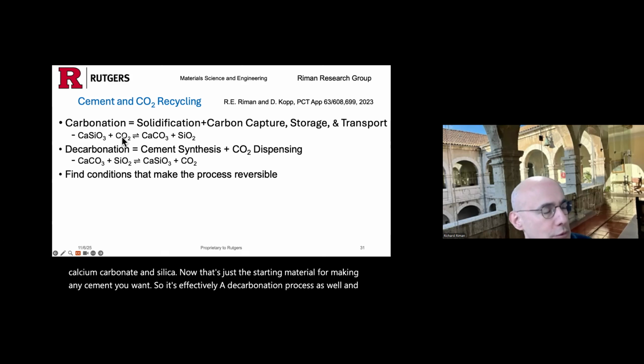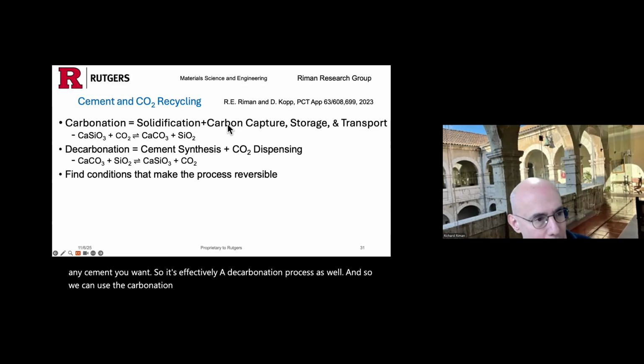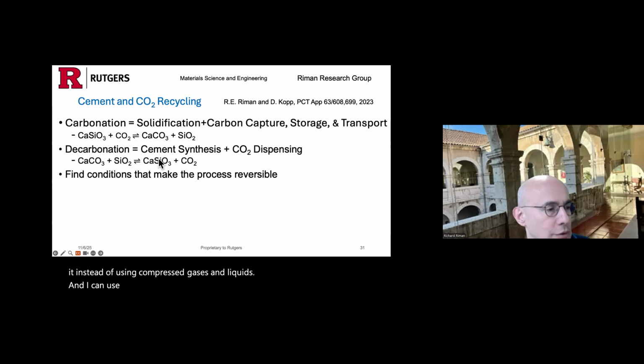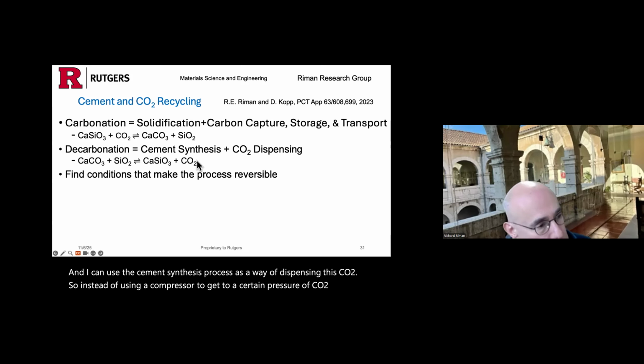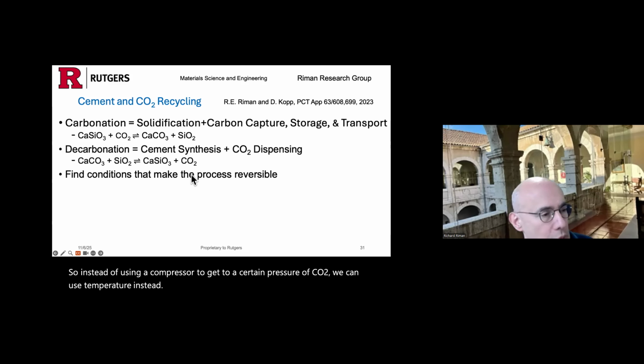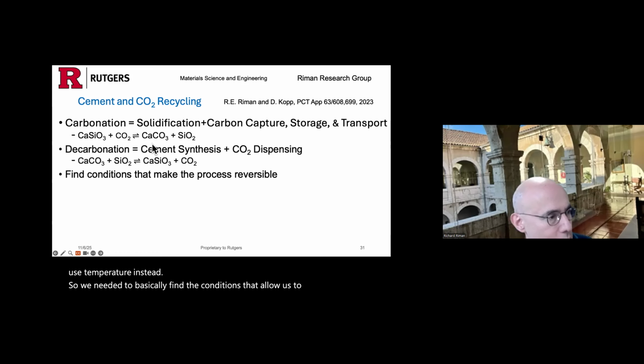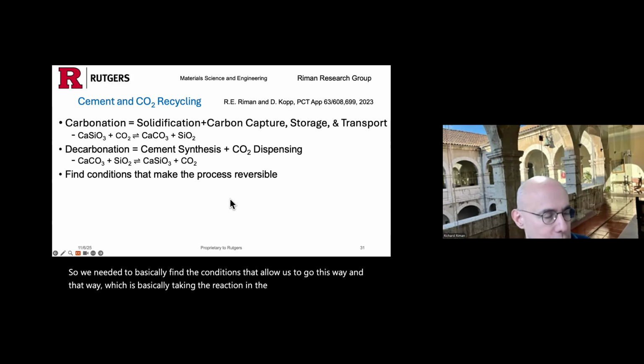And so we can use the carbonation process to capture carbon, store it, and transport it instead of using compressed gases and liquids. And I can use the cement synthesis process as a way of dispensing the CO2. So instead of using a compressor to get to a certain pressure of CO2, we can use temperature instead. So we needed to basically find the conditions that allow us to go this way and that way, which is basically taking the reaction in the forward and the reverse direction.